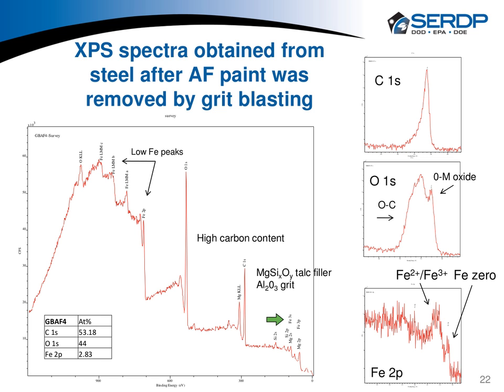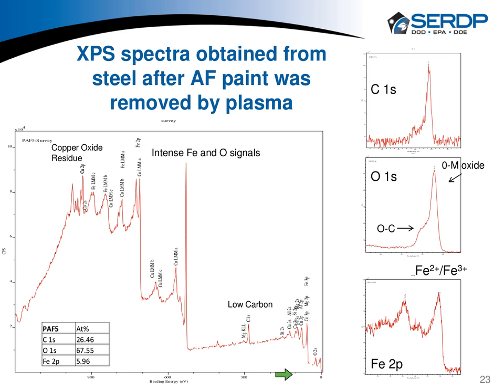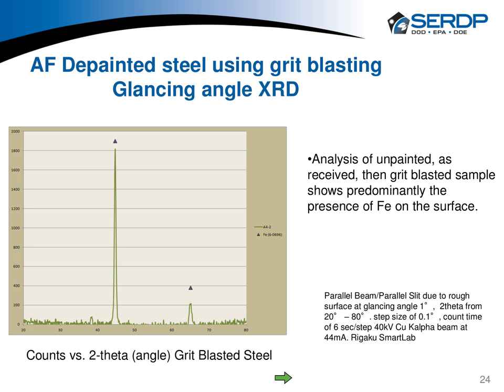We also saw in this sample residue, some from the paint itself and some from the grit that was used to affect the blasting. So if we think about this process, we've got a highly energetic kinetic media impacting a surface, and one can envision that in low areas, say the valleys, the grit may not be able to reach into those areas to affect complete removal, so there's probably always going to be a little bit of paint remaining with grit blasting. That's not necessarily always the case, but certainly in this case, it appears that there's some paint remaining.